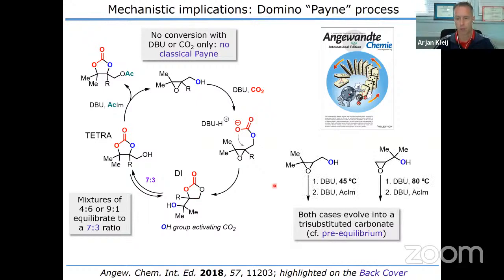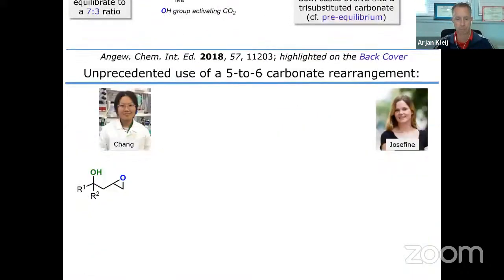As a third proof, we took basically two different starting materials, and if our hypothesis would be true, then it would lead to the same product, and this is exactly what we see. So we get a tri-substituted carbonate being formed from both starting materials under more or less similar conditions. Of course, in this case, this is a tertiary alcohol that needs to be activated at slightly higher temperature, that's normal, but we get essentially the same yield and the same selectivity in these reactions. So that is proof for the existence of a pre-equilibrium at the carbonate level.